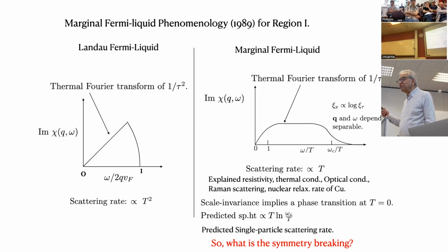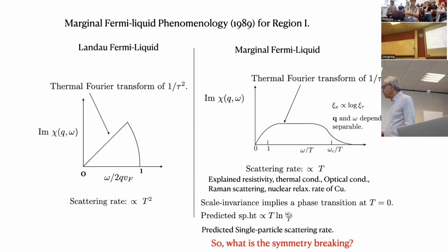You should think what would happen if the spectrum goes as log of tau. If there's log of tau, there will be ground state entropy. It's forbidden, if you believe in the third law, which I don't really do. Okay, so if you now Fourier transform this, the imaginary part of this object goes as omega divided by temperature. There's no scale in the Hamiltonian, and then it will become a finite value until you put some short time cutoff tau c, or a high frequency cutoff omega c.